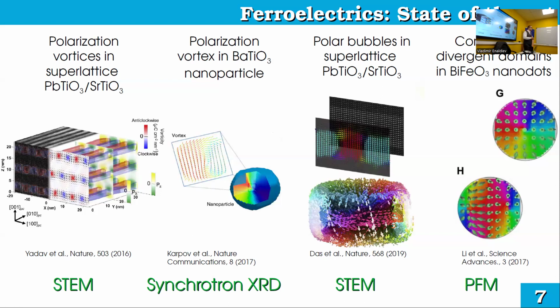Wait, what do you mean by STEM? Scanning transmission electron microscopy. But does it map not spin but ferroelectric moment? No, okay, I will make a comment here. Basically, you fill some lattice, and you have a virtual undistorted lattice. You put one onto another and calculate polarization based on displacement of ions. Okay, it's very simple. So it doesn't directly measure polarization.